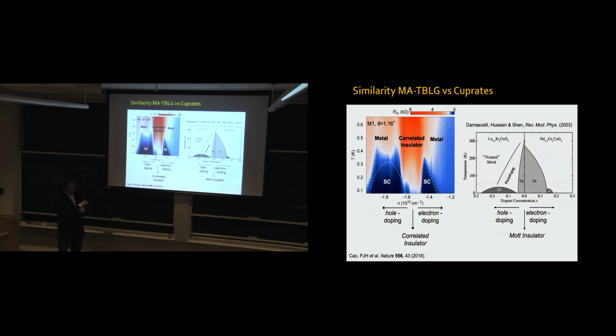Here we have a correlated insulator state when we put half as many electrons as we can in these bands. If you add a few electrons, you get a small superconducting dome. If you add a few holes, you get a larger, wider superconducting dome.